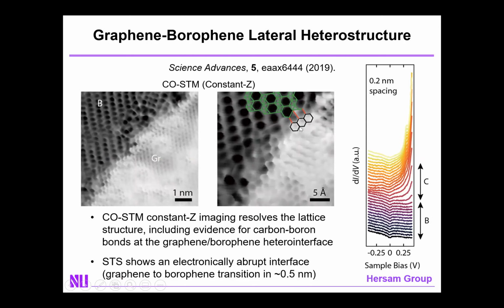And this is, I think, somewhat surprising. Normally, when you have a lattice mismatched system, it requires many lattice constants before you can return to the pristine atomic structure. And I think the fact that it's so abrupt, despite the poor lattice matching, is further indicative of the polymorphic nature of boron.